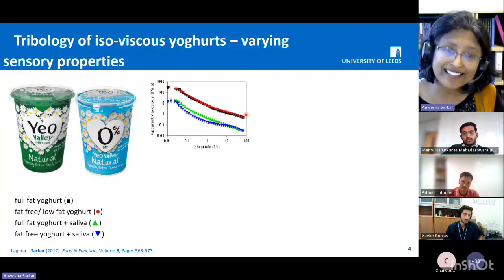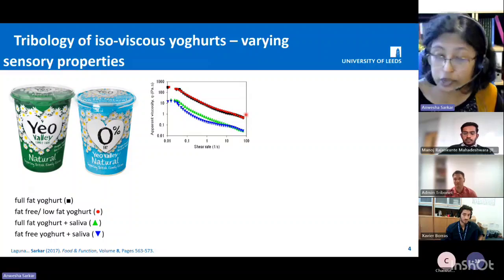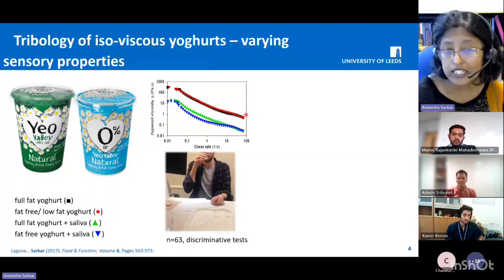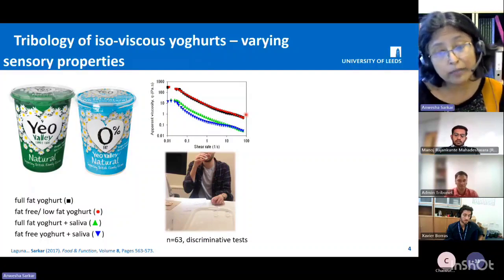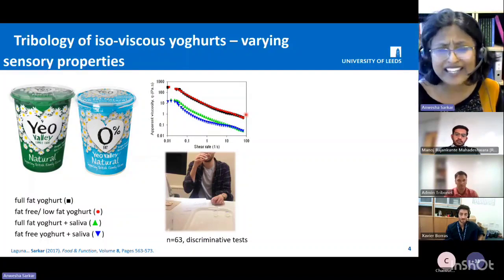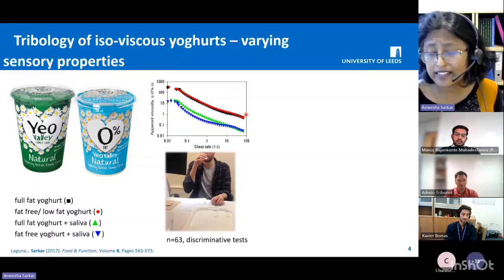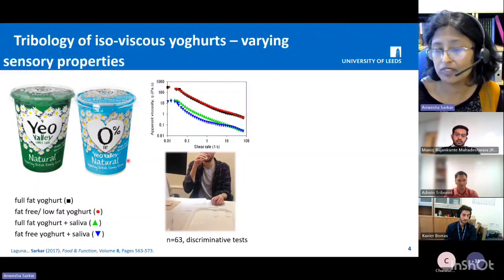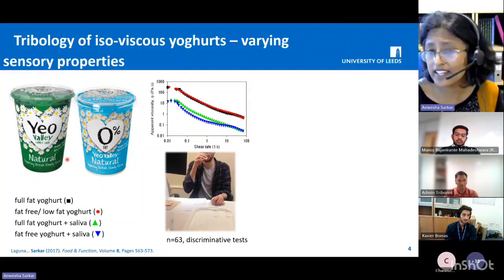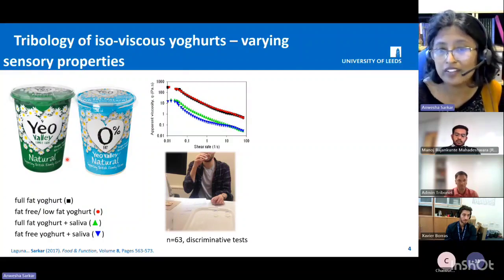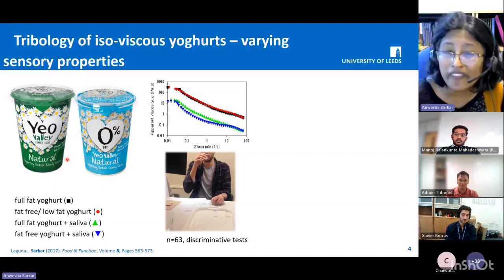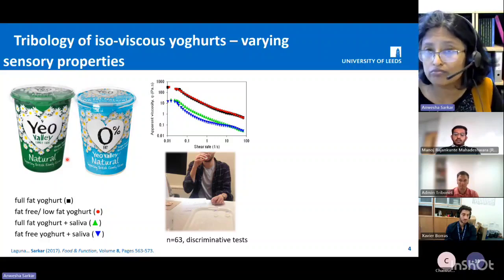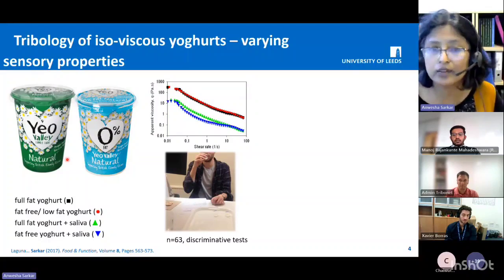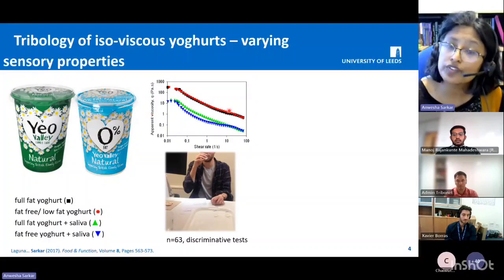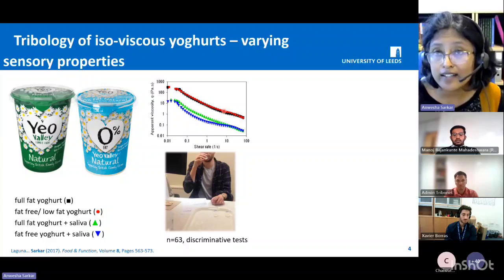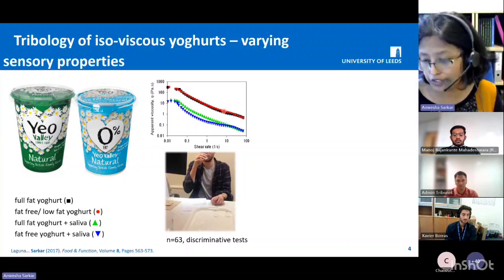So we thought, let's test this material with human beings. And we did a discriminative test with 63 participants, and statistically they could easily identify. These were blind tests, and they could easily identify that this is low fat and this is high fat. And they said that the low fat was very, very watery, non-thickened, whereas the high fat was much more lubricious, creamy, and so on. But bear in mind, they were isoviscous.